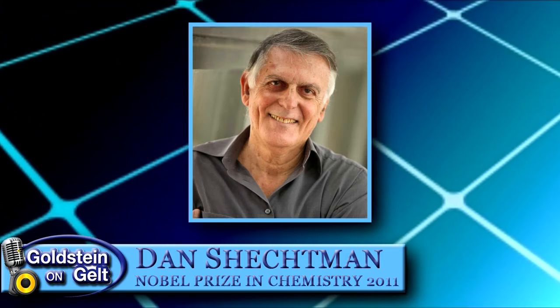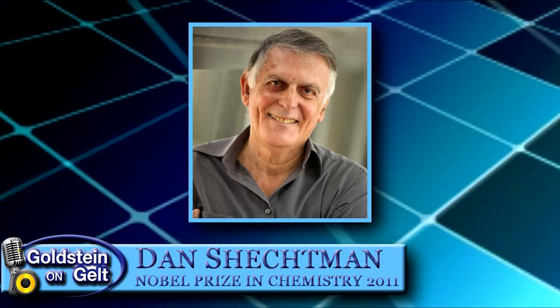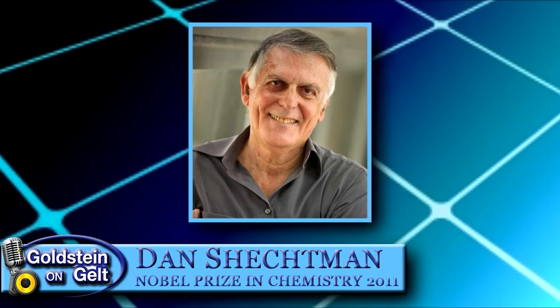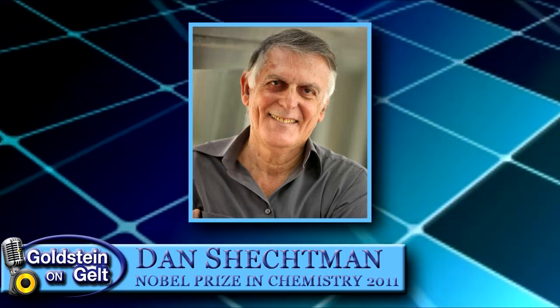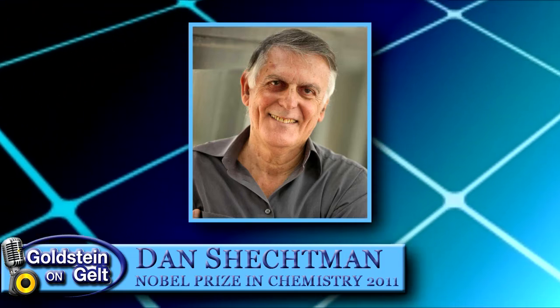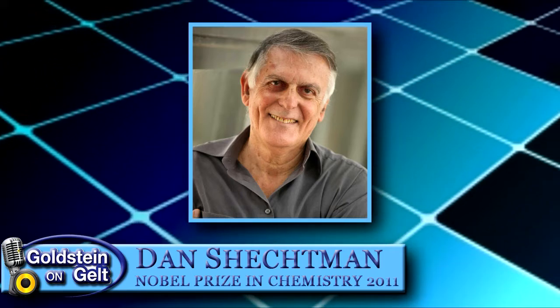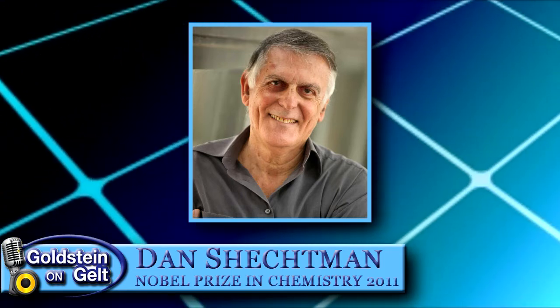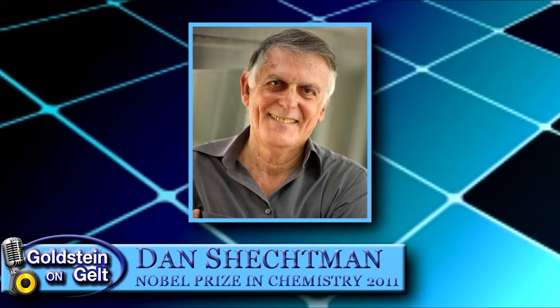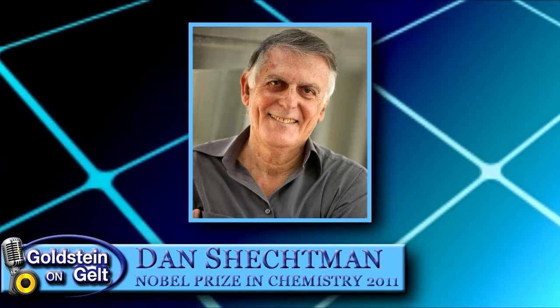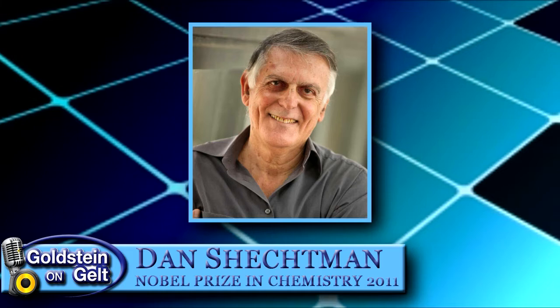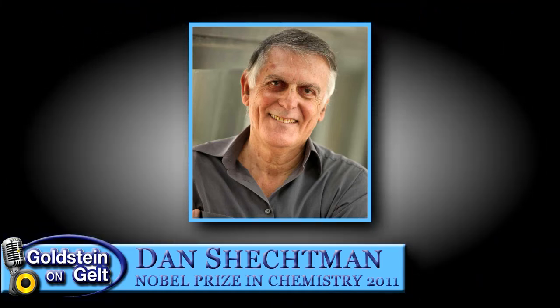So if I stop the line and ask you to continue that, you would know how to do it, because there is order and periodicity. Now, the quasi-periodic materials are ordered, but there is no periodicity. If I ask you to continue to build it, you will not know how to do it unless you obey certain matching rules, and then there will be no repeating motif there. But there is order.